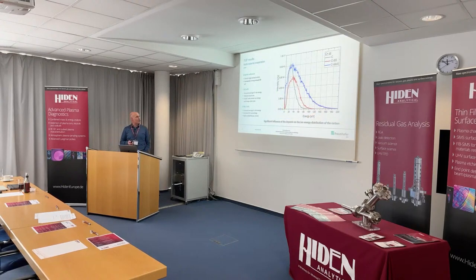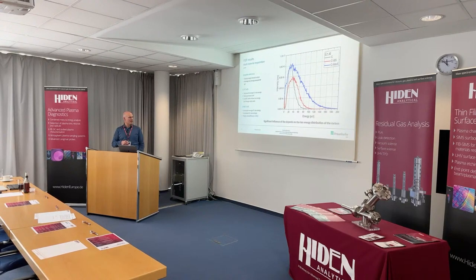Okay, now I put it together. Always the C plus for the 3 different cathodes. All the other process parameters are the same. And we see now the reference in carbon. Then we see some movement to higher ion energies if you put boron in it. And if you put molybdenum in it, then it moves straight to the right side. And of course, we affect the properties of our films with it.